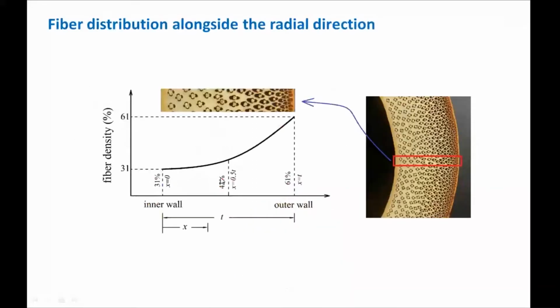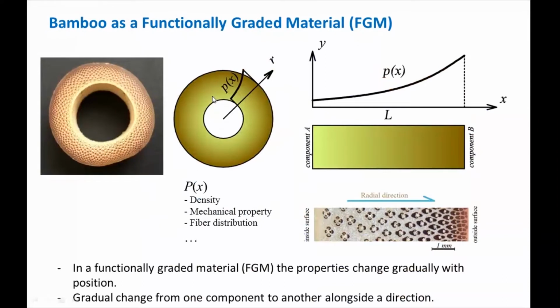You can see from the internal wall to the external wall, the most concentration is in the external wall, and the minimum concentration of the fibers is in the inner wall. For example, 31% at the inner and 61% at the outer layer here. And you can see a schematic graph presenting this. Yes, it's bamboo as a functionally graded material.